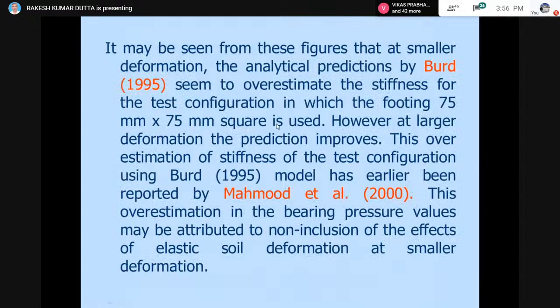Finally, this was the main conclusion drawn, and a similar conclusion was also reported by Mahmood et al. in the year 2000, that Burd's model overestimates the bearing pressure in the initial part of the curve because of the non-inclusion of the elastic soil deformation effects at small deformation. So the conclusion of our study conducted in 2002 also matches with the conclusion drawn by Mahmood et al. in 2000.